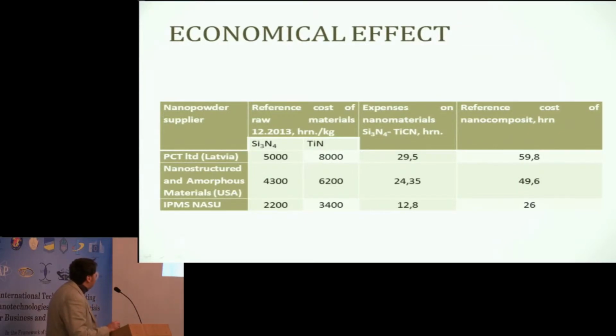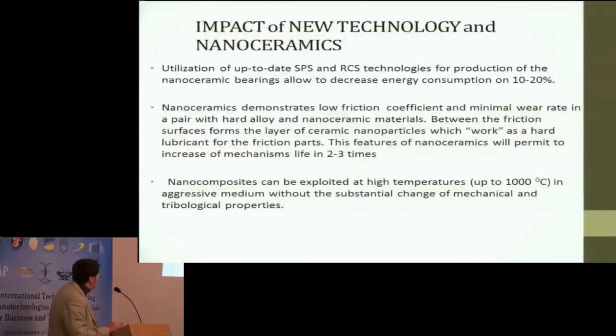Some tribological properties of our materials. We tested them in dry sliding contact in pair with steel 100Cr6, in pair with cemented carbide, and in pair with nanocomposite. We found that the best pair to assemble hybrid bearings is nanocomposite in pair with hard alloy, and much better is nanocomposite paired with nanocomposite. You can see the decreasing friction coefficient, and after the fitting-in period the wear rate of the material stabilizes.